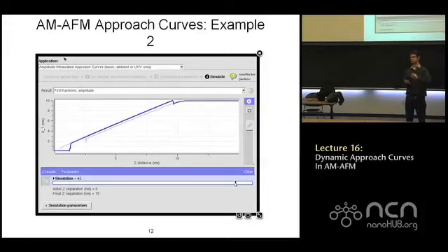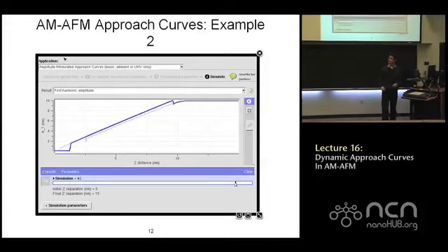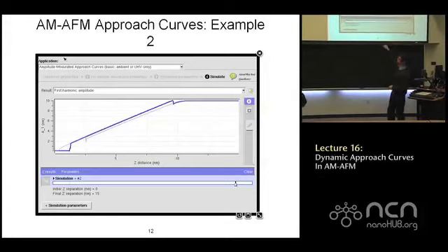It's a little bit more complicated now because the tip is vibrating around a little bit, but basically this is the same phenomenon. There's a bistable region for the equilibrium of the tip stuck onto the sample and popped off of the sample. But in addition, there's a second bistable regime, which is attractive and repulsive, having to do with attractive and repulsive regimes of oscillation.